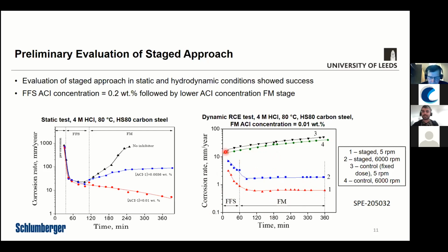You can see the sort of dramatic difference between the inhibitor efficiency and the low corrosion rates just by simply having that film forming stage initially, which has a dramatic influence on ensuring that the protective film is formed, and then the film is maintained by much lower concentration of inhibitor. Whereas for lines 3 and 4, where that initial film forming stage wasn't applied, the corrosion rates are much higher because the initial film that formed wasn't essentially protective enough for the duration of that experiment.